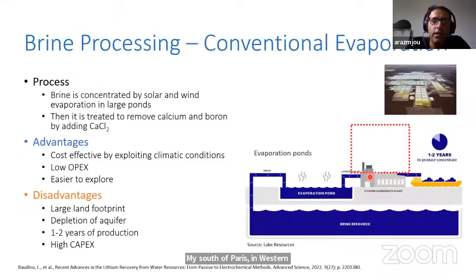In terms of processing, brine processing is currently based on the concentration of brine by solar and wind evaporation in large ponds, and then it is treated to remove calcium and boron by adding reagents. The advantage of this conventional evaporation process is the cost. It is very cost effective by exploiting the climatic conditions, with low OPEX, and easy to explore. The main disadvantages are large land footprint, depletion of aquifer, 1 to 2 years of production, and high capex.